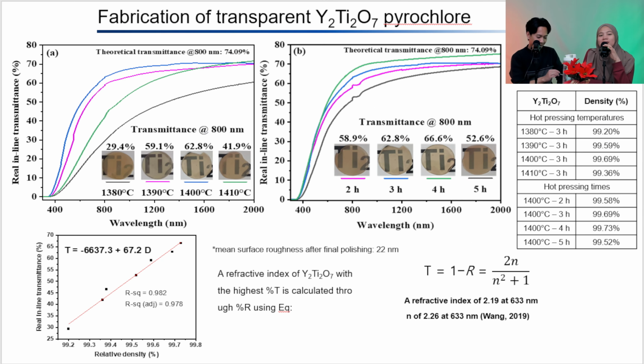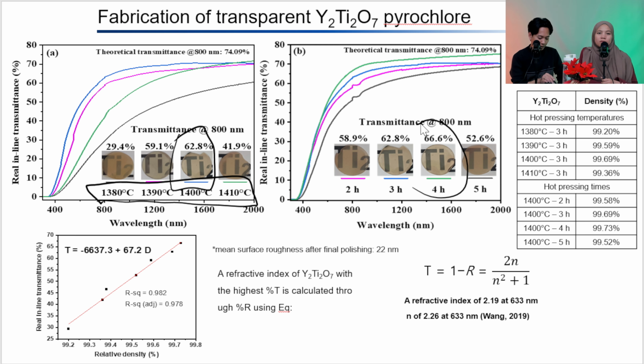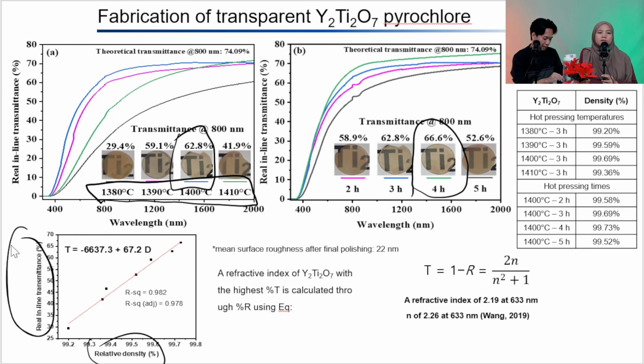Thank you. And you see, by modifying the sintering temperature, we can get different transmittance because of the different density, and also by modifying the sintering time, we can achieve the highest transmittance of 66.6%. We can see the relationship between the relative density and real in-line transmittance is a positive linear relationship.